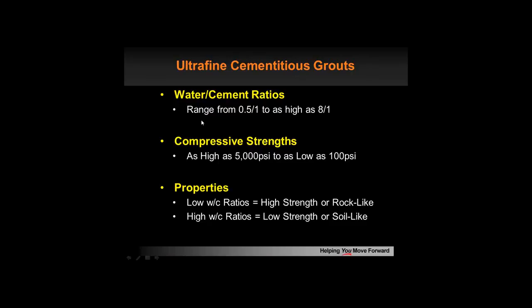Some of the value adds for ultrafine cements that we see for those mixes is you have a variety of ranges of water cement ratios, from as low as 0.5 to 1 to as high as 8 to 1 in some parts of the country. Compressive strengths can range as high as 5,000 psi to as low as 100 psi. A low water cement ratio is going to equal a high strength or rock-like finished grout, whereas high water cement ratios are going to equal low strength or a soil-like grout.